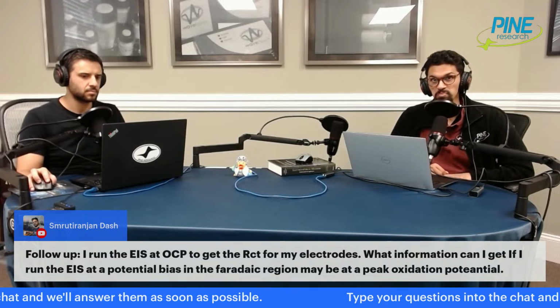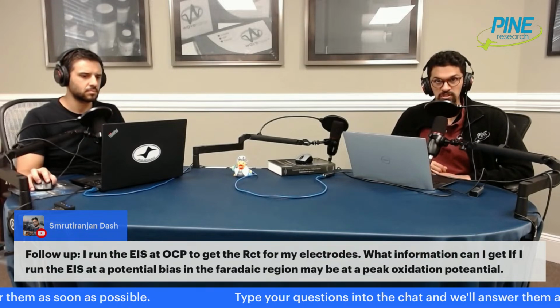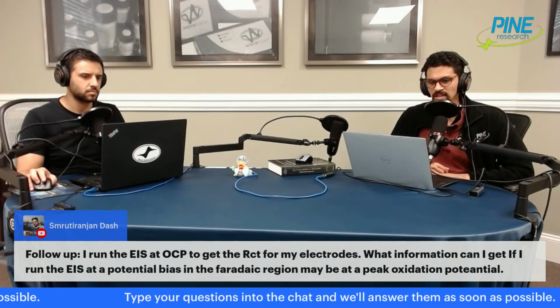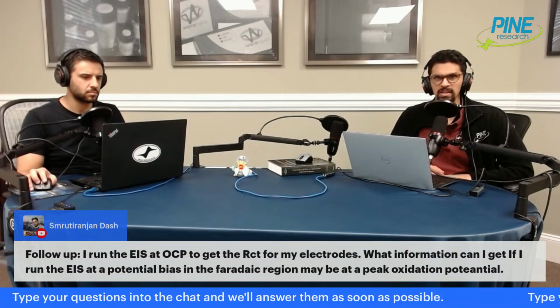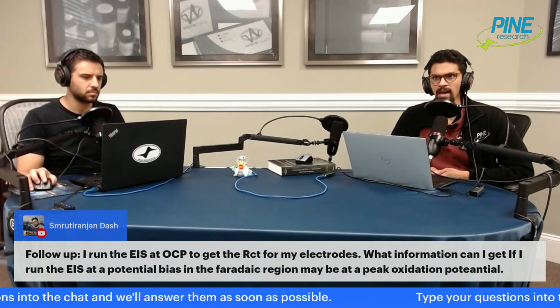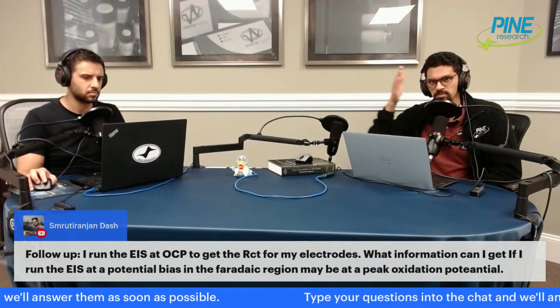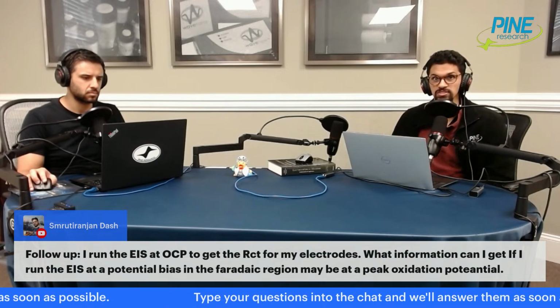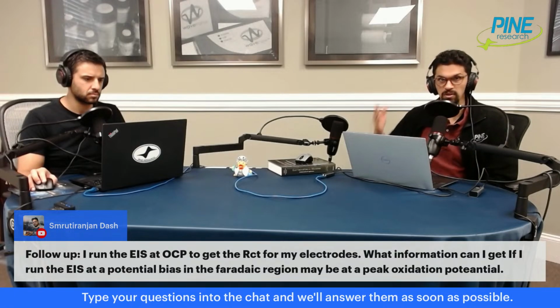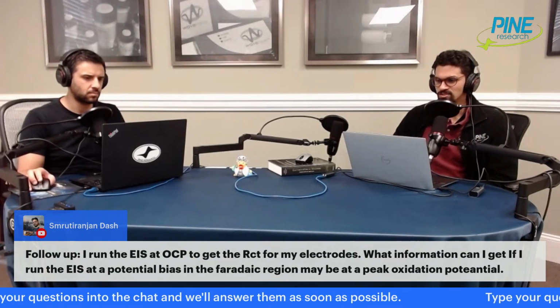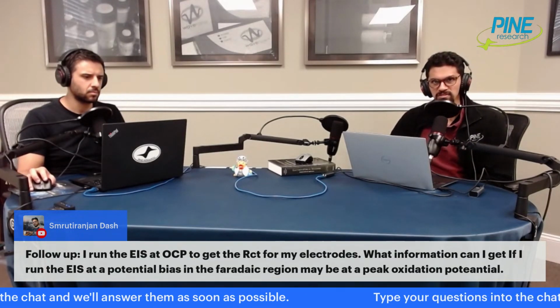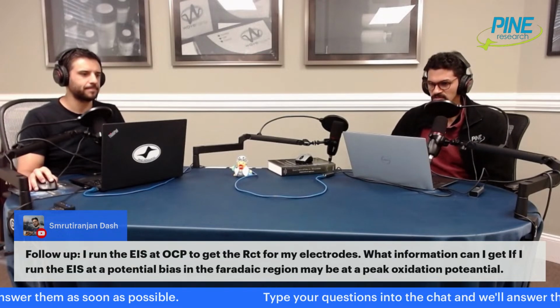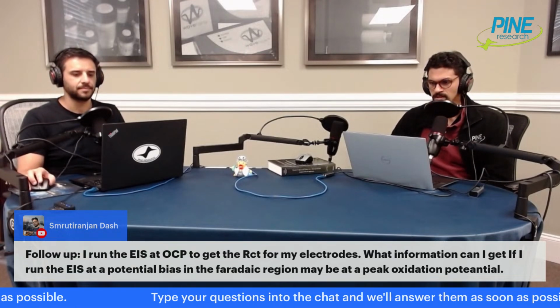You may actually find if you go past the E naught, which is a good thing, you'll get a little bit more information. But I think a lot of people do EIS at multiple potentials, and they look at how the RCT changes over time, or at each potential. And that's a very indicative thing of what's going on in their system.